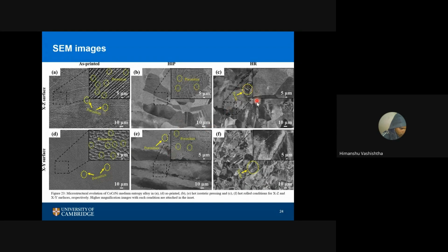And when we hot roll it, it changes everything. During hot rolling, new crystals are forming, you can see twins were there, and the porosity has been almost eliminated in this case. You cannot find the pores there the way they were available before.